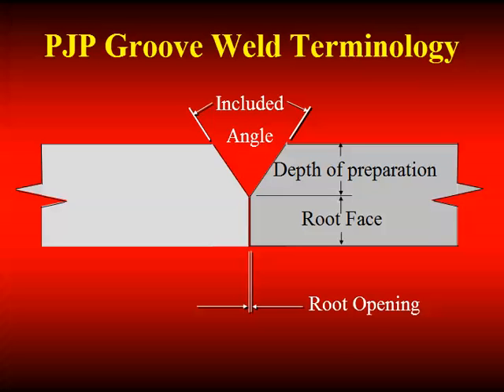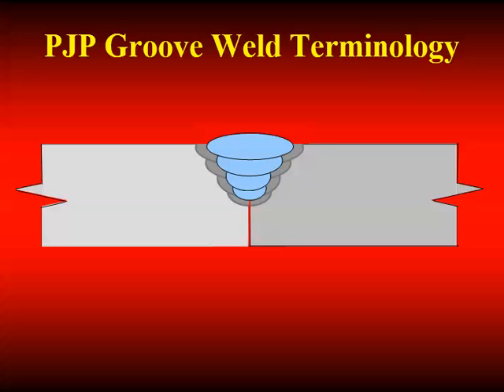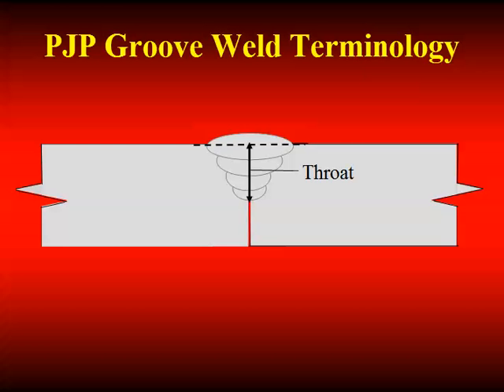I've shown this with zero root opening or near zero root opening. We may have a deliberate gap in there as well. We weld up that joint, and once again we have the heat affected zone just like we had with our complete joint penetration groove weld. We get no credit for the reinforcement left over on the cap of the weld. The throat of the weld is defined as the distance from this upper surface down to the fused root region.